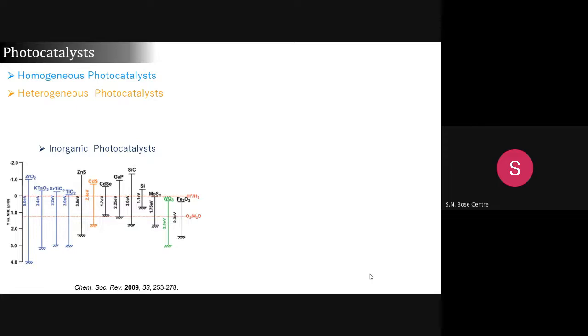While if you see the TiO2, it does not have sufficient gap, although it can do it, but this will be more futile than this one. So they have tuned the band gap in different ways to harvest maximum light and play with the driving force to reduce the hydrogen.